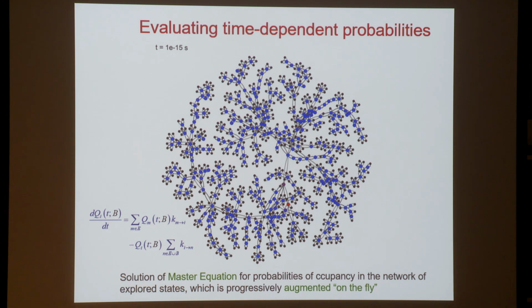We have devised an algorithm for solving the master equation in such a network that is progressively augmented on the fly, with absorbing boundary conditions on the boundary states. And one can watch this probability diffusing out from the original point here. We have a diffusion of probability outwards as time goes by. Red here means high probability, blue means low probability, and you can see how the system, as time goes by, visits more and more states in its configuration space. This can be taken out to something like 1 millisecond. That's where this will actually end. And we see that many states are being visited. Some of them are not visited so much, and the probability distribution becomes broader.